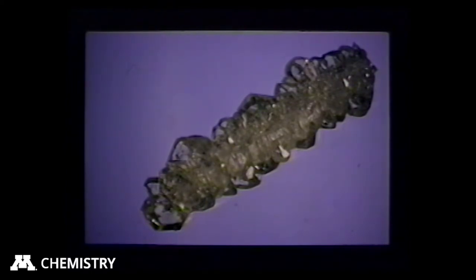We can also see this phase transformation when the crystals are not in solution but are out in the open, just sitting on a benchtop. So if we remove the needles from solution before this has happened, we get crystals that look something like this. And the dark part is where the phase transformation has begun to take place. The clear part is the untransformed metastable crystal. And so I'm going to show you a sequence of slides here. Keep your eye on this clear part here and see how it changes over a period of time as we continuously take these pictures. We're taking them over a period of days here.